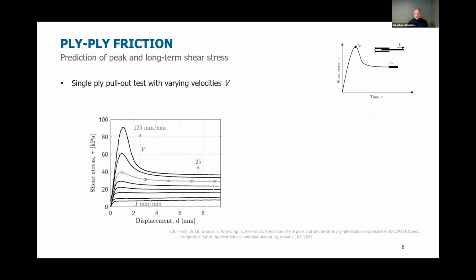Well, let's have a look at this single ply pull-out test, where we vary the rate or the speed with which we pull the layer from between the others. So in our curve, we see with increasing speed that our peak grows and we reach a certain plateau of the long-term shear stress. The gray line here depicts the average with error bars of the same measurement conditions on various samples. So you see that the deviation is smaller than the difference between the averages. So that's good.